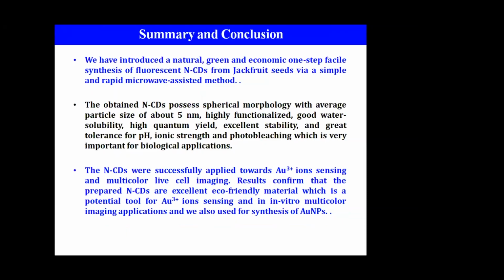Now, to summarize this material: we took the natural green material and converted it into carbon dots, which gives a morphology of size on the order of 5 nanometers. It has excellent stability, very high quantum yield, very good water solubility, and is highly functionalized on the surface. That is the reason it could sense gold ions, which finds a lot of application towards biology. This is a very interesting aspect, and it also works as a fluorescence or luminescence sensor for gold 3+ ions, which is interesting.